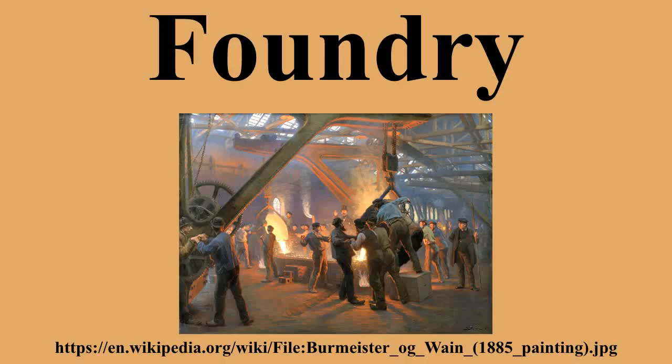Degating. Degating is the removal of the heads, runners, gates, and risers from the casting. Runners, gates, and risers may be removed using cutting torches, band saws, or ceramic cut-off blades. For some metal types, and with some gating system designs, the sprue, runners, and gates can be removed by breaking them away from the casting with a sledgehammer or a specially designed knockout machinery. Risers must usually be removed using a cutting method, but some newer methods of riser removal use knock-off machinery with special designs incorporated into the riser neck geometry that allow the riser to break off at the right place.